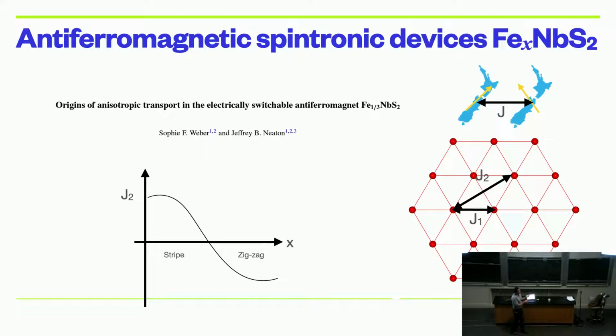And this is a little bit like what I wanted to happen, which was the exchange scale changing sign. It doesn't actually change sign. The main exchange scale, J1, the dominant one, doesn't do anything. But the next nearest neighbor one seems to evolve from one to the other. And because of that we change from one kind of interaction to the other. So it wasn't quite what I wanted. It wasn't quite a system on a critical point.